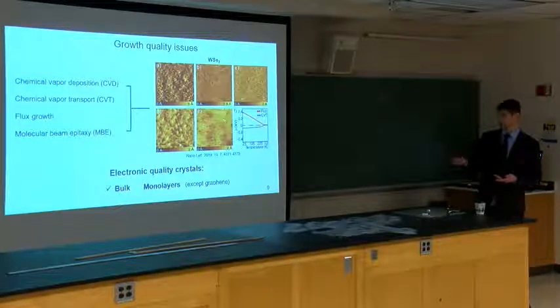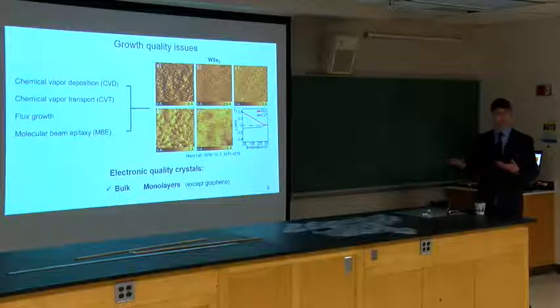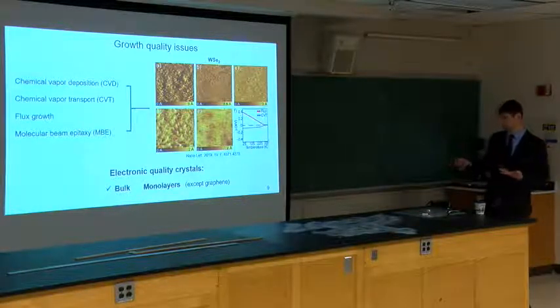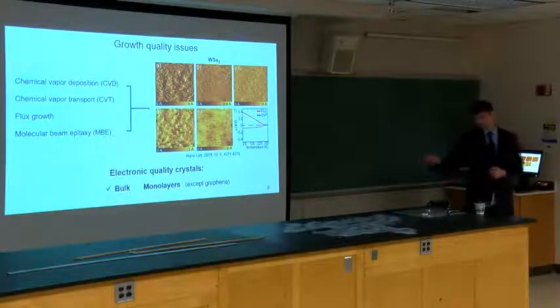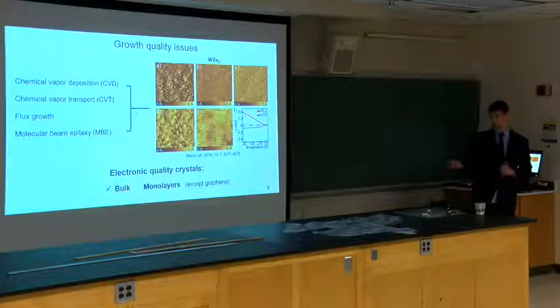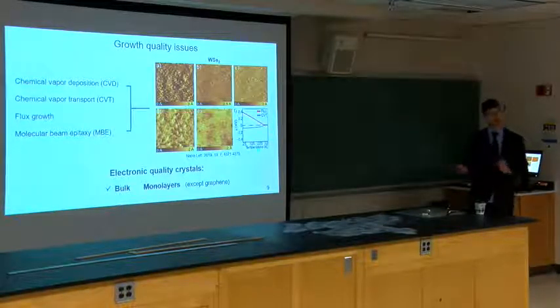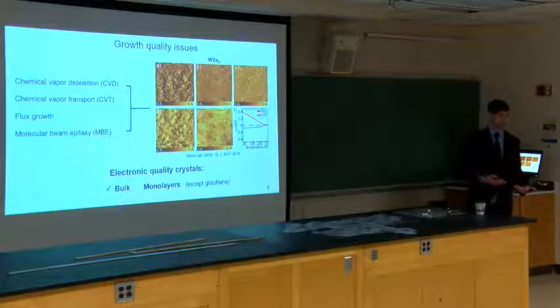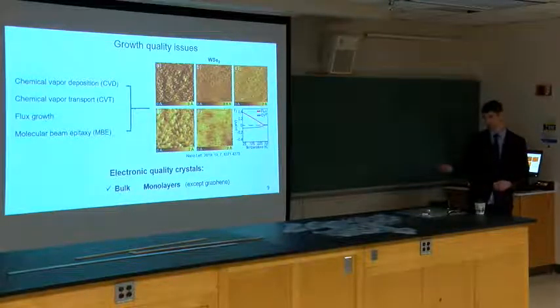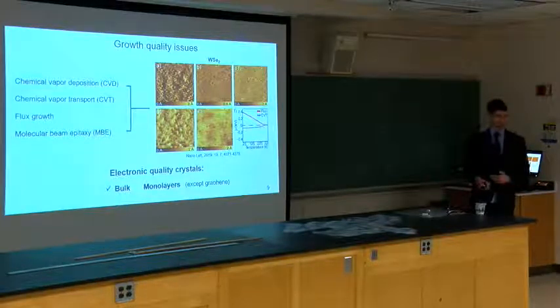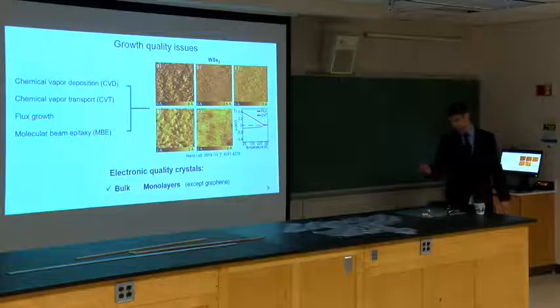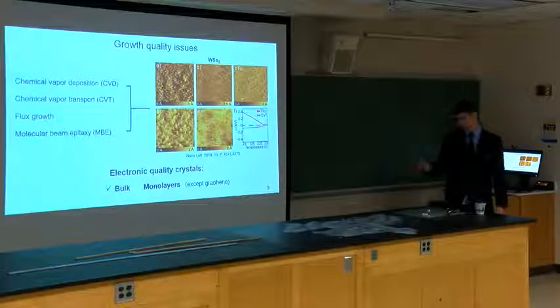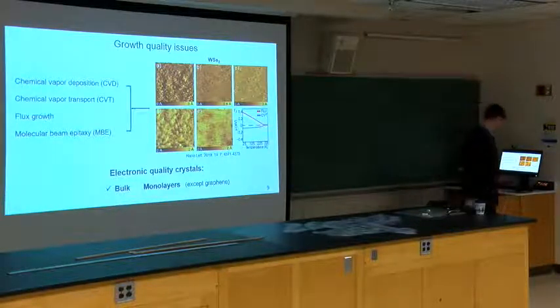So the scale here is 500 nanometers. You can see there's still quite a lot of defects. This is tungsten selenide, so we still have a long way to go. For electronic quality crystals, you can still get it from bulk, but you have to judge where you're getting the material from, and the source matters a lot. And for monolayers, it's really complicated thus far. I don't think we have any perfect electronic growth reports, except for graphene, of course.